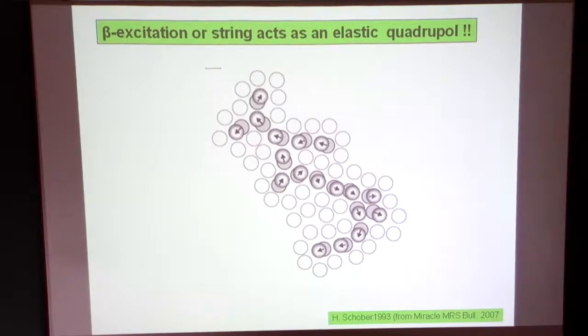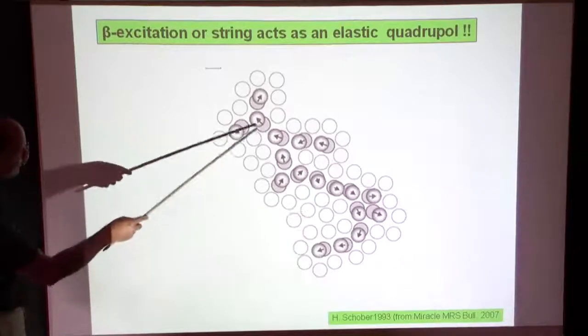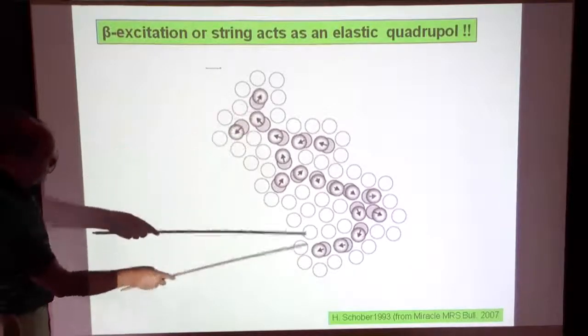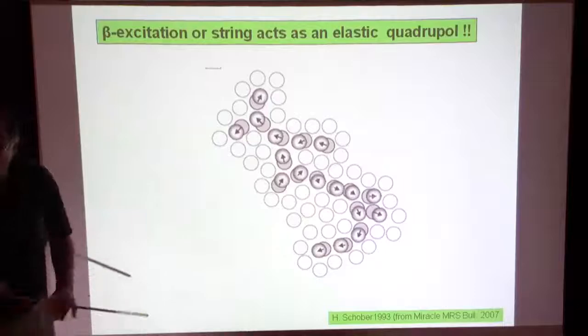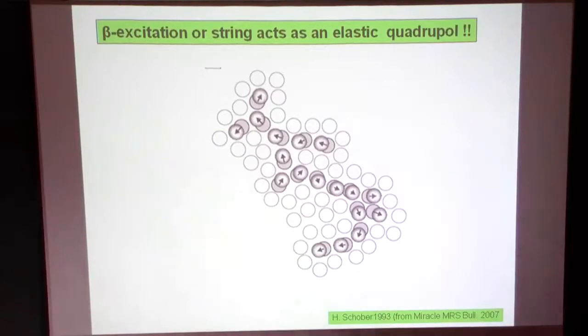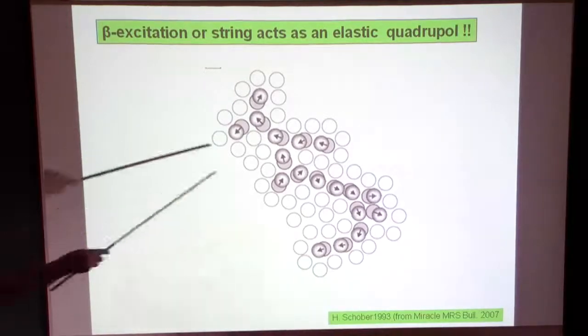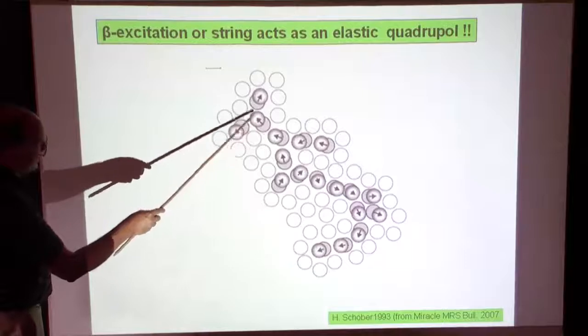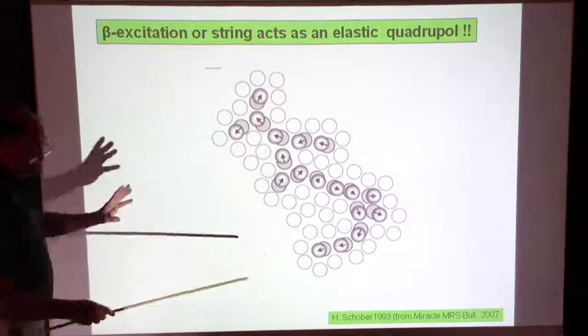which goes with the beta relaxation certainly, because you stay in one meta basin and then you just relax and can come up and forward again. This is reversible, and so the idea of this string is actually that there is some movement in the atoms, small movement of individual atoms, which makes there is no cavity for a vacancy-like type of diffusion. So there is only small motion which go upward then and triggers then the whole arrangement.